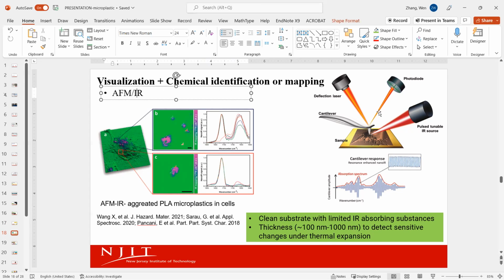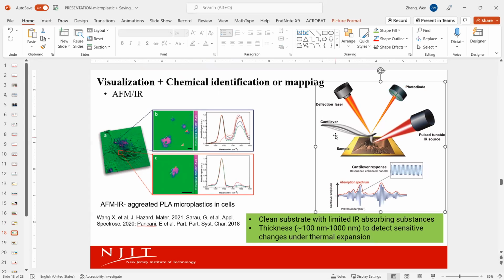So if you combine AFM with IR, as you see from the image to your right, you have a regular AFM configuration here. You have a cantilever, which responds to the sample when the cantilever tip approaches the sample surface. The surface will certainly have interactions like attractive or repulsive forces against the AFM cantilever. This tip vibration is measured by a laser beam. As you can see, there is a deflection laser, and the deflected laser signal is captured by a photodiode. So this is how AFM works. In addition to the regular AFM, here there is a pulsed tunable IR source. Basically, there is an IR laser source, like a laser pen.